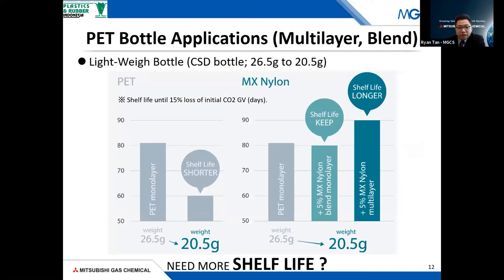So as I mentioned previously, by extending the shelf life of the PET bottle, you are able to consider going for lightweighting, making it a more environmentally friendly approach by reducing the amount of PET used. If you were to look at a 26.5 gram PET preform as a normal monolayer, by reducing it to 20.5 grams, you are able to achieve the same shelf life by incorporating 5% of MX nylon blend. Or if you were to go to multi-layer, even though you have dropped the weight by 6 grams, you are able to extend the shelf life longer. So this is where MX nylon is able to help in all these various applications for the bottles.